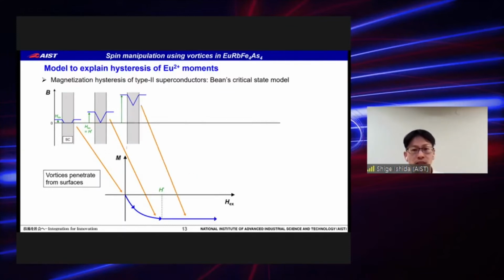With further increasing field, this shape of the B profile inside the sample is maintained, and B goes up. Here we assume constant Jc against magnetic field, so the field dependence of Jc is not considered.